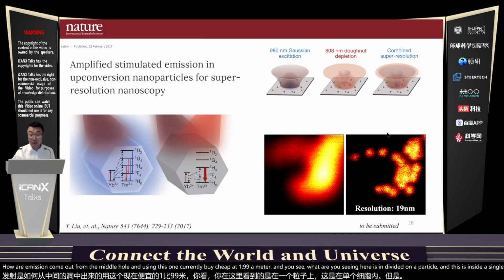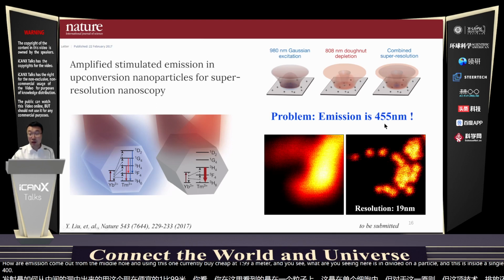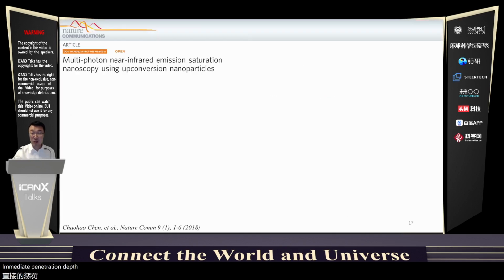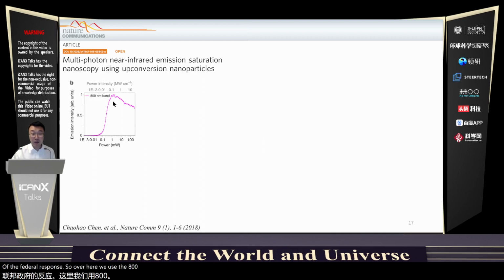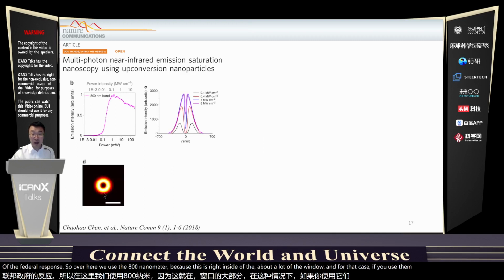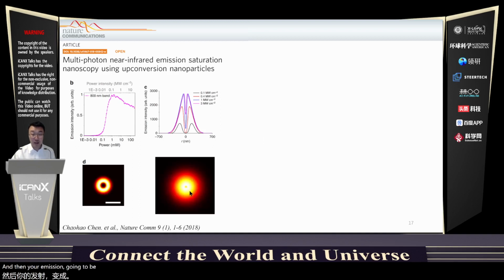But for this technology, the emission is still at 455 nanometers, which is visible and has really limited penetration depth. Therefore, we developed another technology, based on the saturation of the optical response. Here we use 800 nanometers because it's right inside the biological window. If we use a donut beam as the excitation, then your emission is going to be a donut as well.